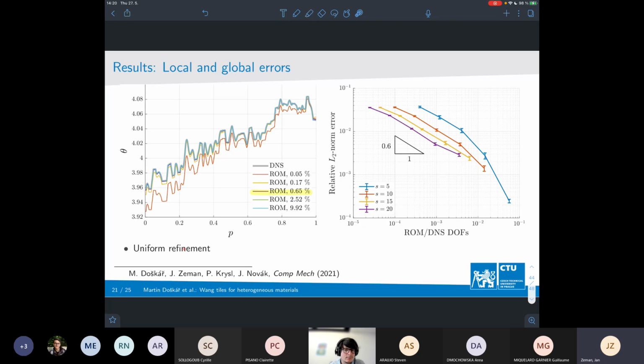And using uniform refinement, we can also have a look how the relative L2 error decays with refining the microstructural mesh, and we can see that it converges. It converges sublinearly, but it's something which is convergent. So, for instance, if you are fine with 1% of your relative L2 error, which in these works is rather acceptable, you can see that you can really reduce your computational requirements in terms of number of degrees of freedom significantly. Again, details can be seen here.